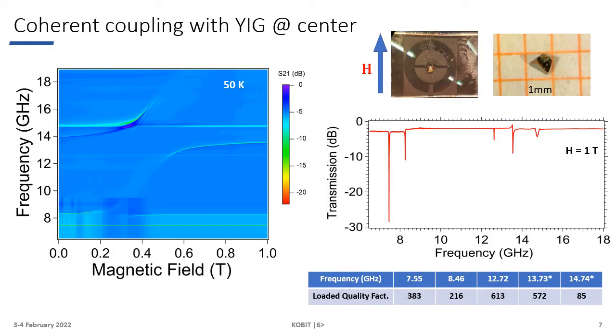We fabricated the resonator by using optical lithography and etching, and we placed an irregularly shaped YIG crystal with edges less than 1 millimeter. The external magnetic field is applied along the microstrip direction. The loaded quality factors of the resonator structure were obtained by fitting the transmission spectrum with input-output formalism, as seen in the table.